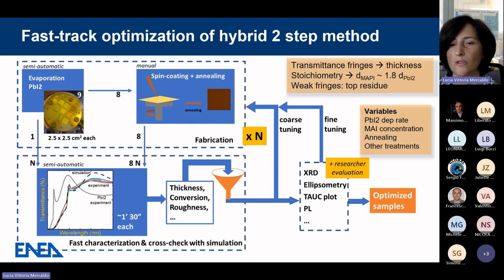So here is a workflow of what we did. The top part is the fabrication stage, the evaporation. The bottom part is the characterization and cross-check with simulation. So we start with the evaporation of the inorganic template. We can prepare up to 9 samples all equal to each other, and then move just one towards the characterization stage and check the thickness of this layer, and all the others move to the spin coating stage and annealing.